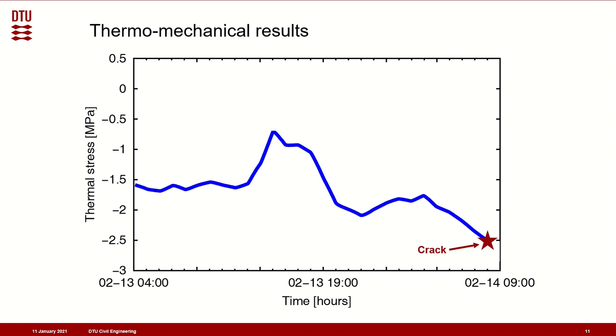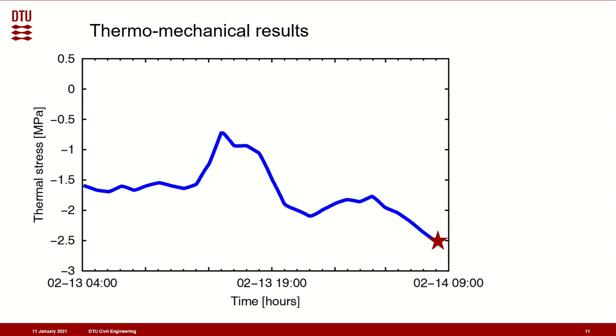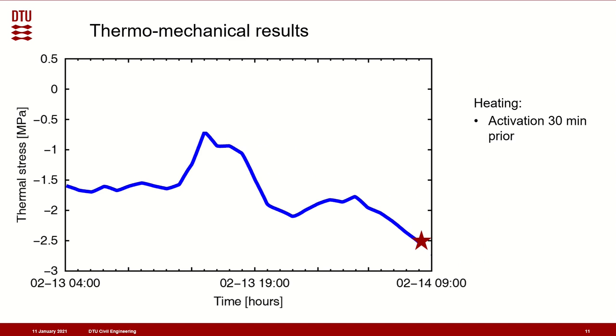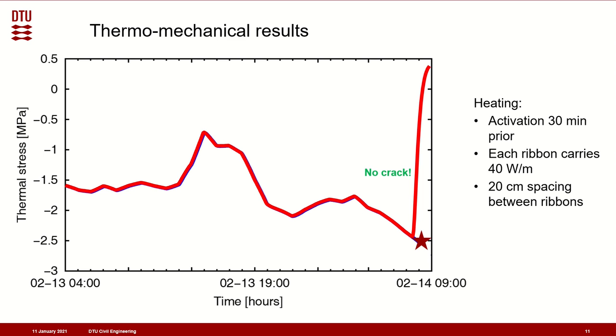Then, thermomechanical calculations were repeated, this time with the heating being activated 30 minutes prior to the identified cracking event. It is considered that each ribbon carries 40 watts per linear meter, and that ribbons are spaced 20 centimeters from each other, center to center. Now represented is the thermostress evolution with the heating activated, and as can be seen, the stresses do not reach the defined tensile strength. With this simulation, it is demonstrated that utilizing an electric snow melting system to protect asphalt pavements against low temperature cracking is deemed possible.